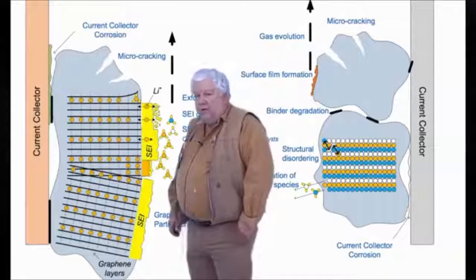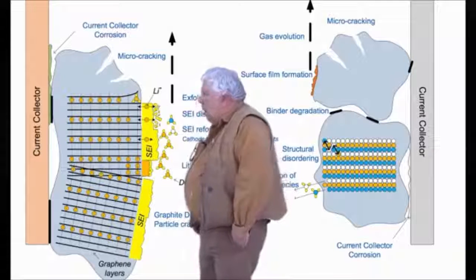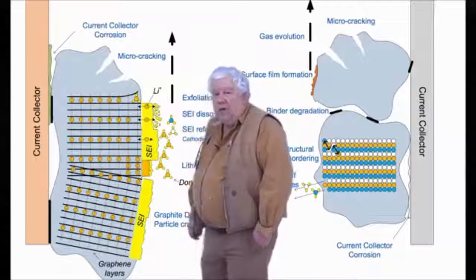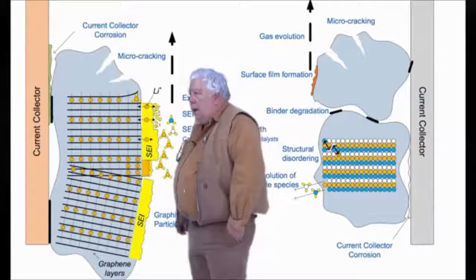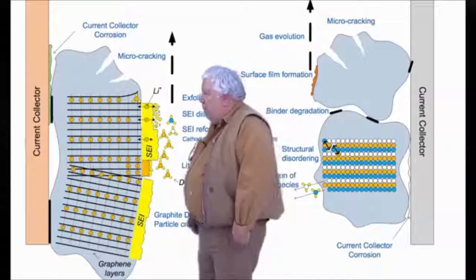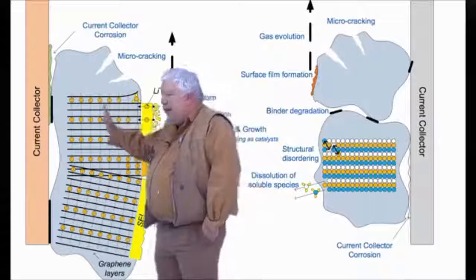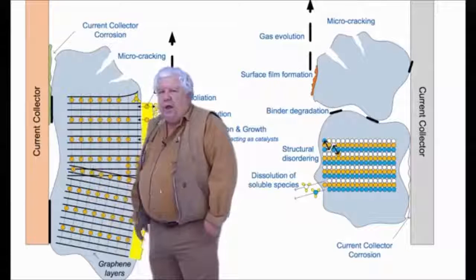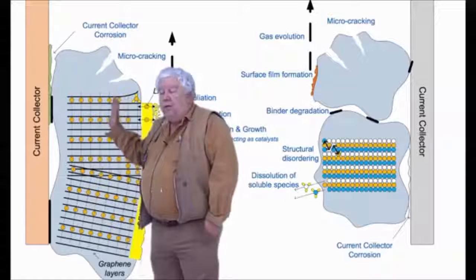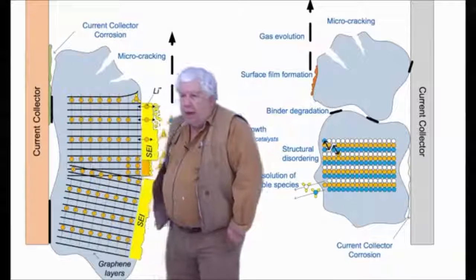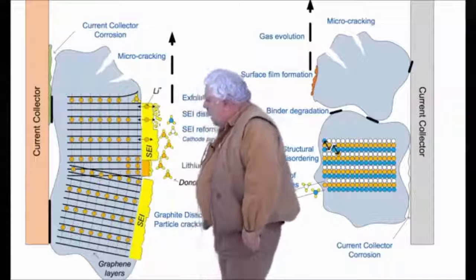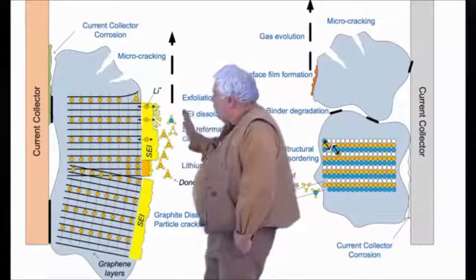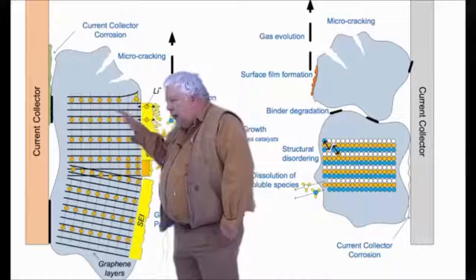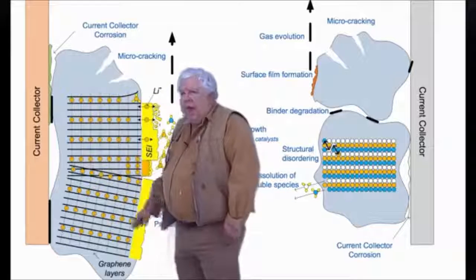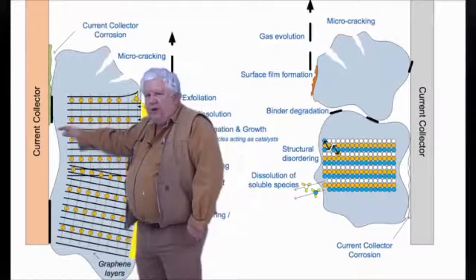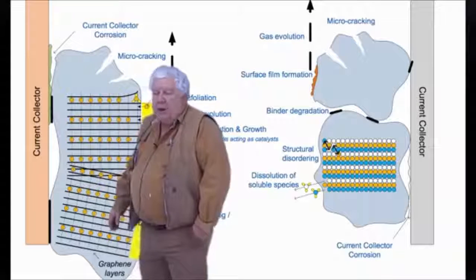Interestingly, in an over-discharge situation, or in trying to charge in very, very cold weather, really for lithium iron phosphate, anything below freezing, the lithium can't migrate through the SEI layer then, and it forms lithium plating on top of the SEI layer, which is not good. But normally, whenever we're charging the cell, lithium ions migrate through the SEI layer and are stored between the graphene sheets on the anode.